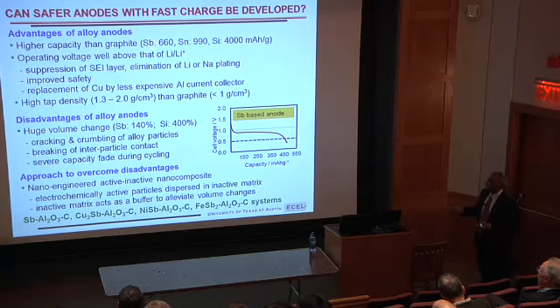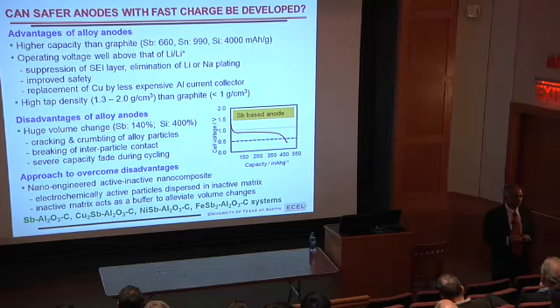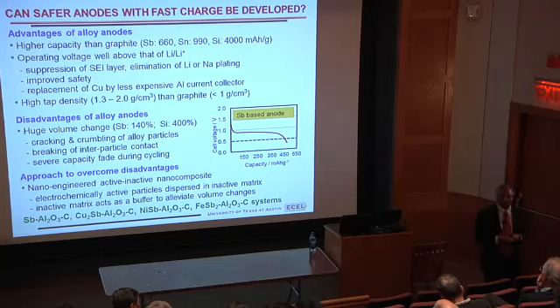But these materials, for example, have huge tap density. Graphite tap density is less than 1 gram per centimeter cube. Silicon is even less, because they have to make it very porous, very nano, with a lot of space to accommodate 400% volume change. Antimony has only 140% volume change. Now, what is the advantage here?